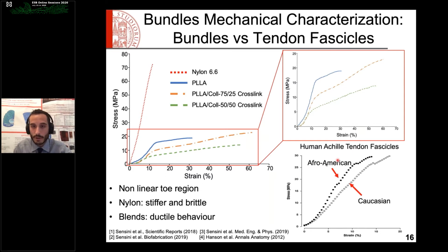Here you can also see a comparison between the mechanical behavior of human tendon fascicles for Afro-American and Caucasian men, reported in literature. What you can immediately see is that all the different bundles show a non-linear toe region, similar to that of tendon and ligament fascicles, with an elastic, stiffer and brittle behavior for the nylon 6/6, while for the regenerative blend we have a ductile behavior, suitable as a safety factor in case of overload of the scaffold in the early stage of regeneration.